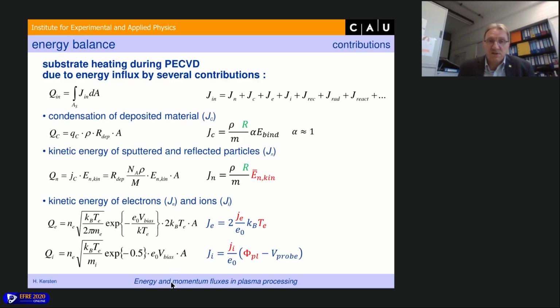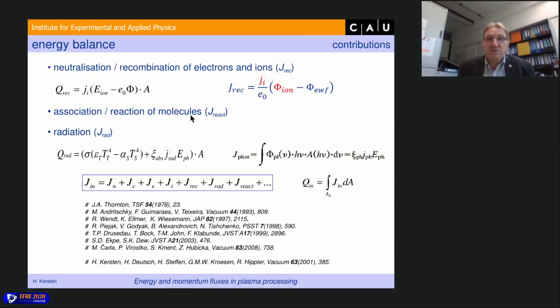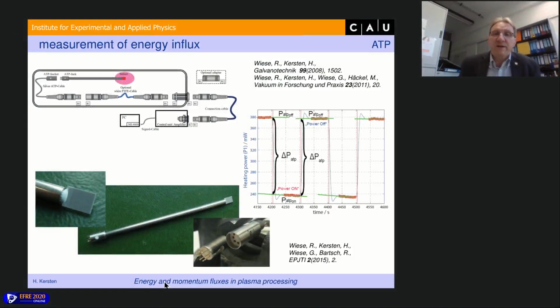This is just an example. Or for the neutralization, if there is recombination of electrons and ions at the surface, you of course need the ion energy and the work function for this material, because it is neutralization. So you can try to address all these processes by a formula, by an equation, and compare this theoretical sum of the contributions with your measured sum of the integral energy flux.